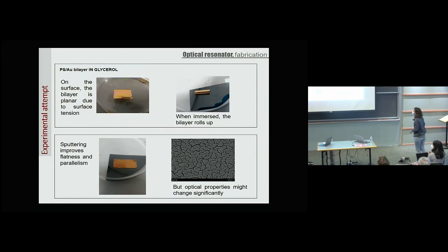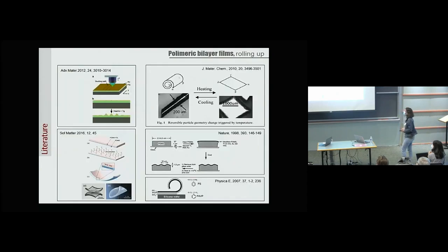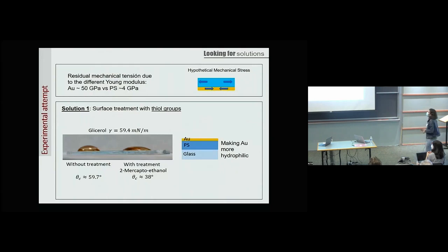They rolled up with the evaporation, probably because of the mechanical tensions we had in the sample. The flatness was better, but of course we were not going to use these samples. We checked the literature and found this rolling up is actually quite standard, and it is used for drug delivery: you heat this roll and then it spreads, and you can release some drugs, or you can do some kind of lithography. We were trying to find solutions to keep our samples flat. We tried other solutions. Okay, let's try to make the gold more hydrophilic, so that we minimize these tensions between the polystyrene and the gold, which are probably related to the different Young modulus of the two materials.